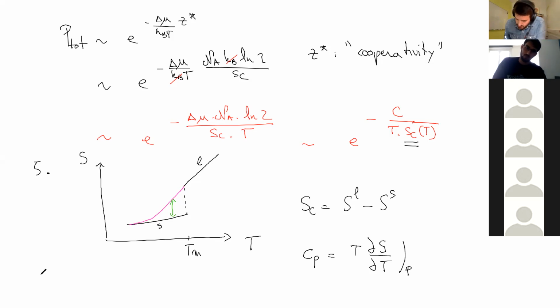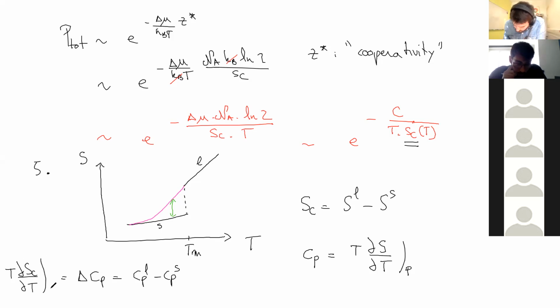So it's interesting, then I can say that S_C is equal to delta C_P, which is C_P of the liquid minus, sorry, what did I say here? It's wrong. Sorry for that. That is correct now. If I derive the configurational entropy with respect to the temperature at constant pressure, multiplied by T, this is the difference of the heat capacity between the liquid state and the solid state. We call that delta C_P, and it's another very important quantity in glasses, and this is something you can measure by measuring how much energy is accumulated inside. I mean, this is the heat capacity, okay? The variation of energy with temperature.